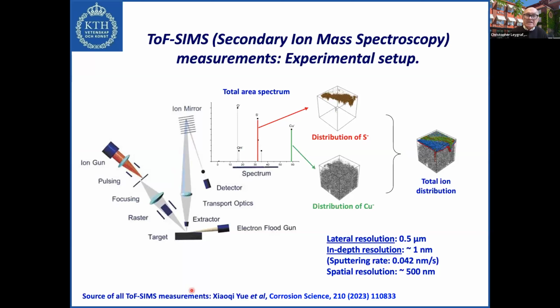The first technique that we have been using, trying to analyze these different elements in copper after exposure to groundwater, is time-of-flight SIMS, time-of-flight secondary ion mass spectroscopy measurements. The experimental setup is seen here. I'm not showing the details, but basically it's an ion gun which hits the target, the sample here, is reflected through an ion optical system, and out comes the total area spectrum, out of which the lateral distribution of different elements like sulfur or copper can be mapped with a lateral resolution of about 0.5 micrometer and an in-depth resolution of 1 nanometer. So this is quite a good tool for analyzing these elements, not only at the surface, but also inside the material.